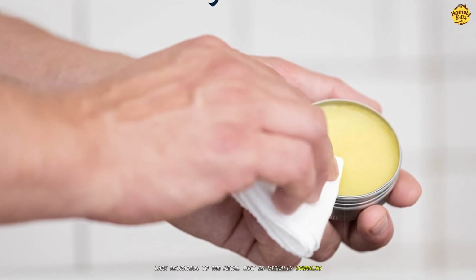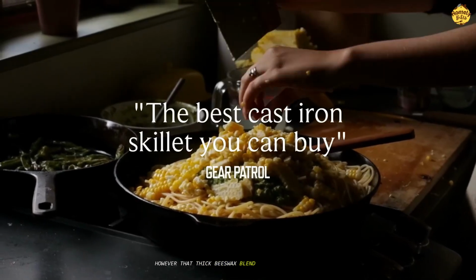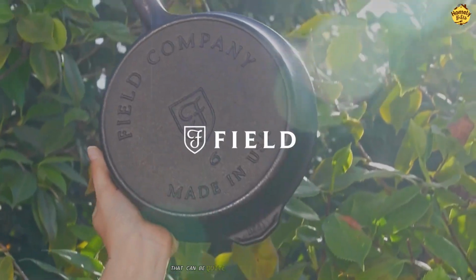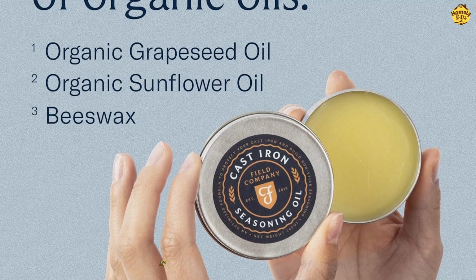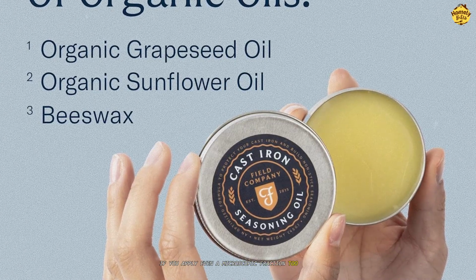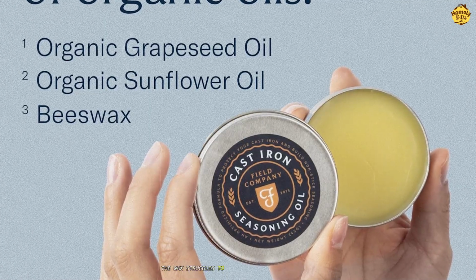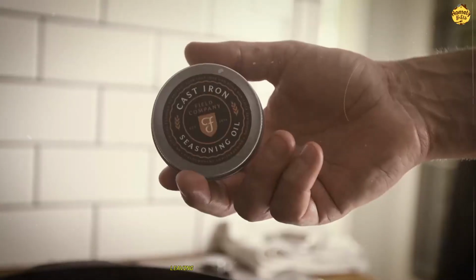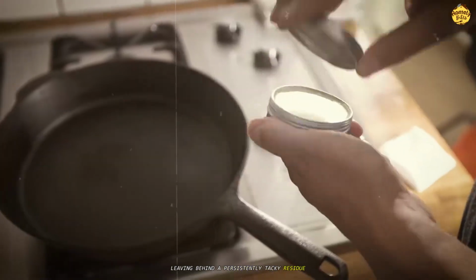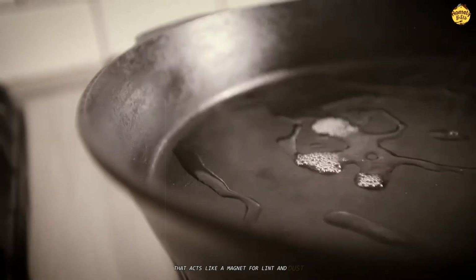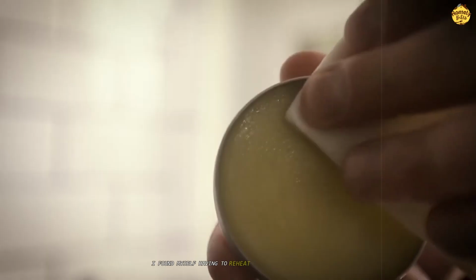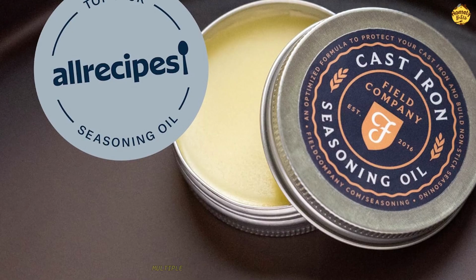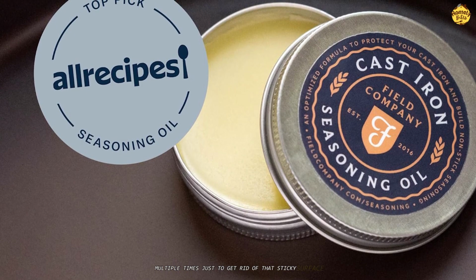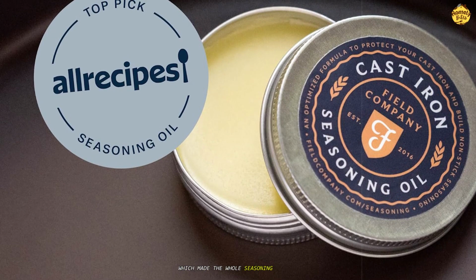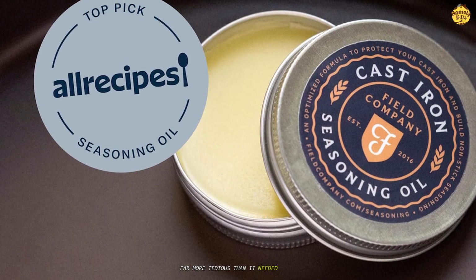visually stunning. However, that thick beeswax blend brings a noticeable learning curve that can be quite frustrating for beginners. If you apply even a microscopic fraction too much product, the wax struggles to fully polymerize in the oven, leaving behind a persistently tacky residue that acts like a magnet for lint and dust. I found myself having to reheat and furiously buff the skillet multiple times just to get rid of that sticky surface, which made the whole seasoning process far more tedious than it needed to be.